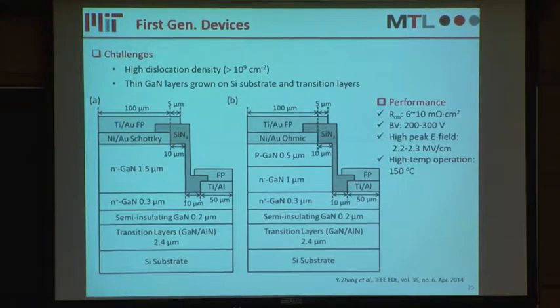Let's look at the performance of this first generation device. The on-resistance is 6 to 10, and although the drift region is only 1.5 micron thick, we can still get a breakdown voltage of 200 to 300 volts, which is really good. All these devices can operate at 150 degrees C without any degradation.